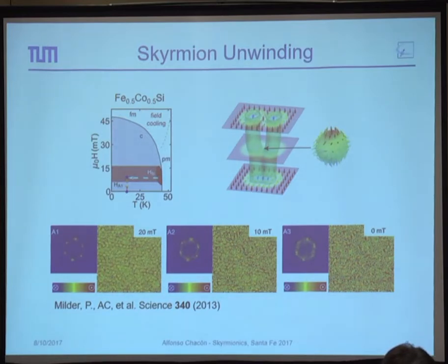It was the work that Emil did, published a couple of years ago. What you observe here, for a 50% doped compound, is about a 90 to 100 nanometer pitch length, so the skyrmions are quite big. Due to the fact that we can go to the lowest temperature, the contrast is also very good.